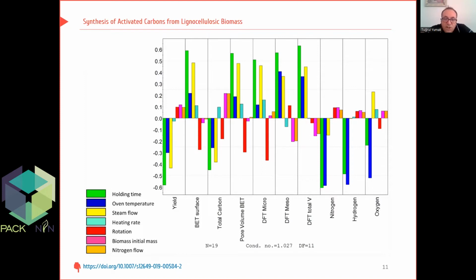For physical activation of peat, as you see, the holding time and steam flow are the most influential parameters on pore size distribution responses. However, the rotation speed also seemed to have an impact on porosity formation, which was likely due to the better contact between the biomass or biochar and the activating agent.